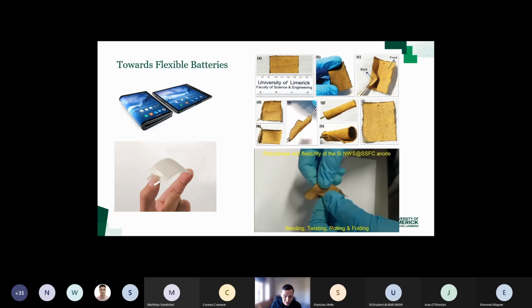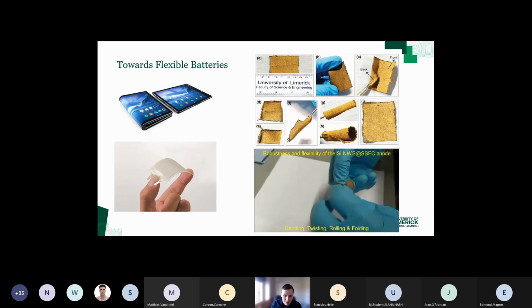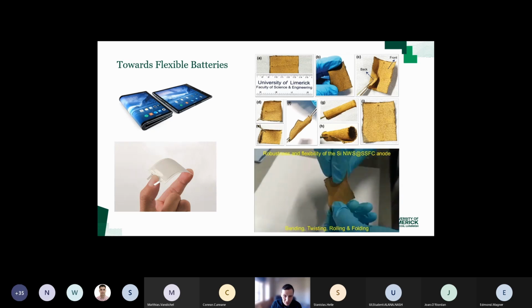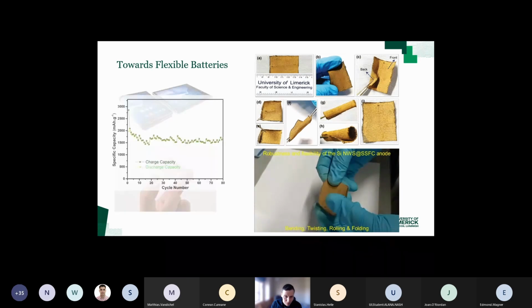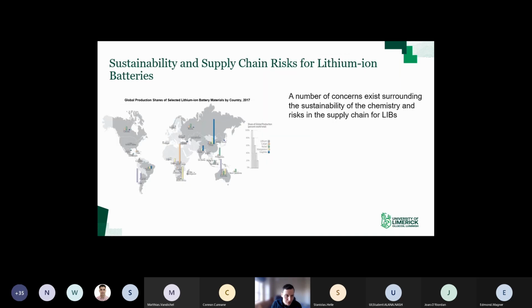Sumer did this very nice video, I have to say, showing how robust that current collector is, even with twisting and deforming it. You can see no material delaminates or comes off the surface, which is exactly what you'd want. Even after the twisting and deforming, he put that into a cell, and you got very good capacity retention as well. So it had no effect on the capacity retention of the silicon, which was great. That's kind of where we are.